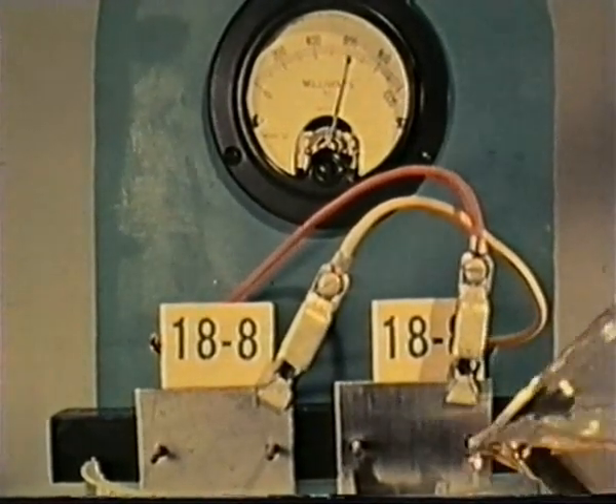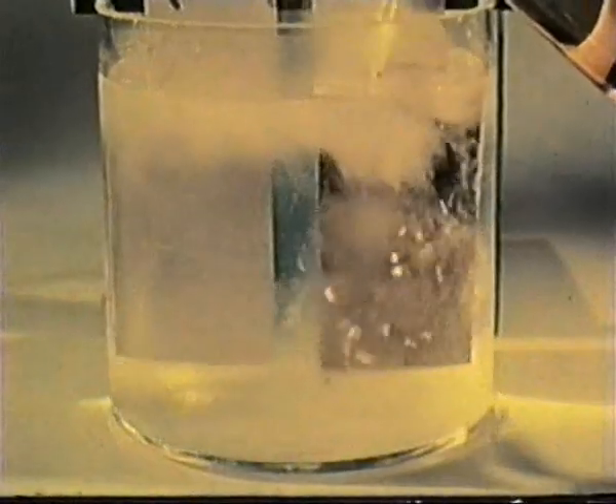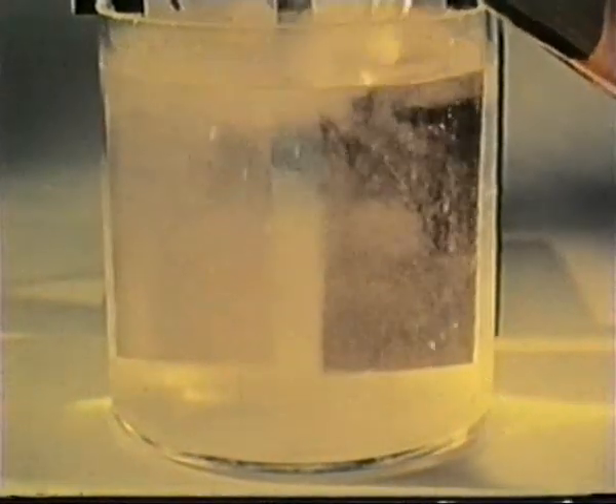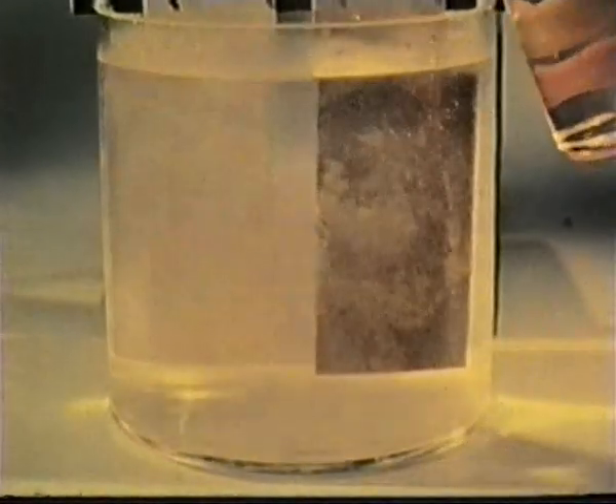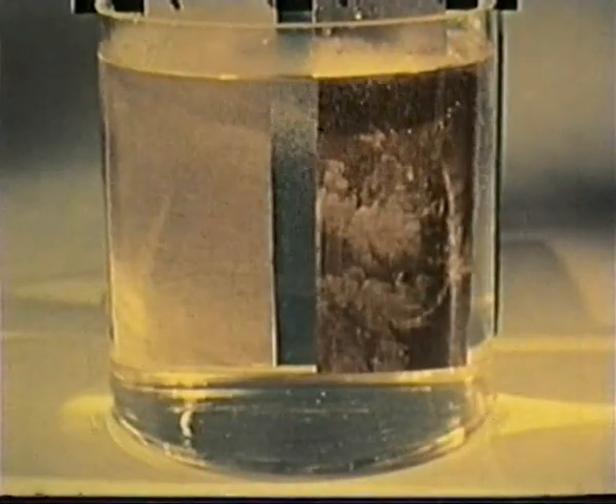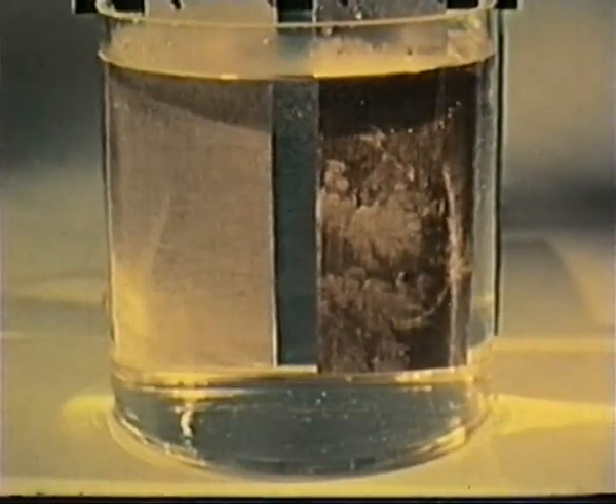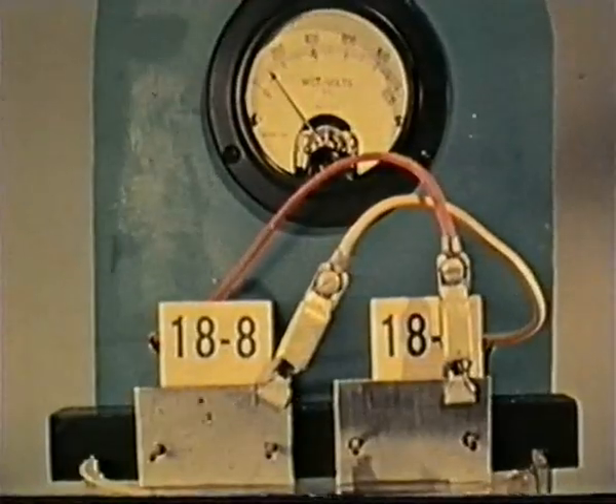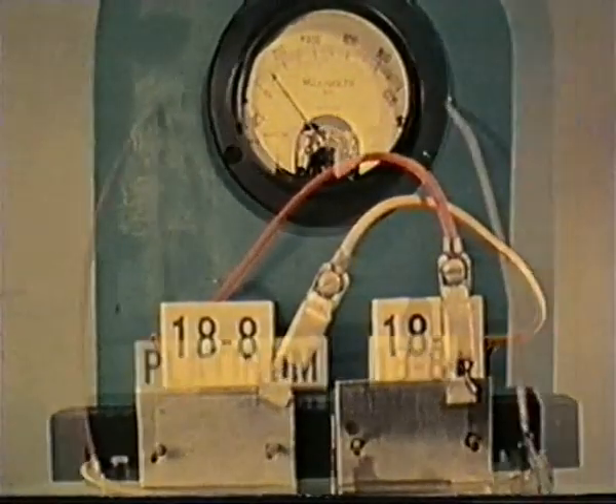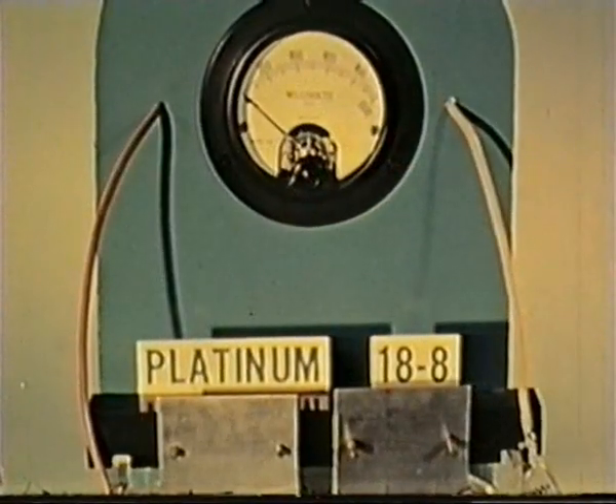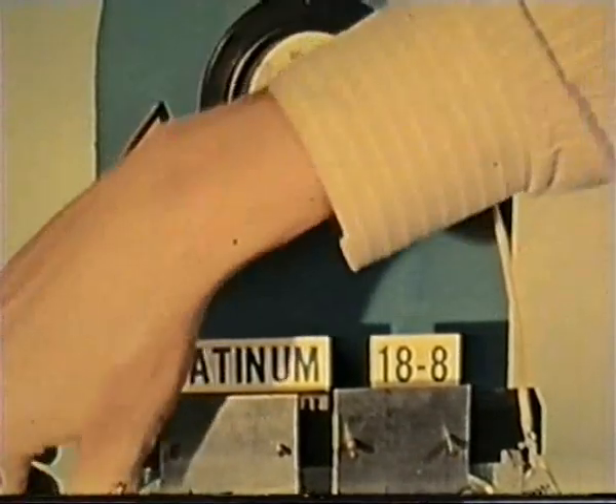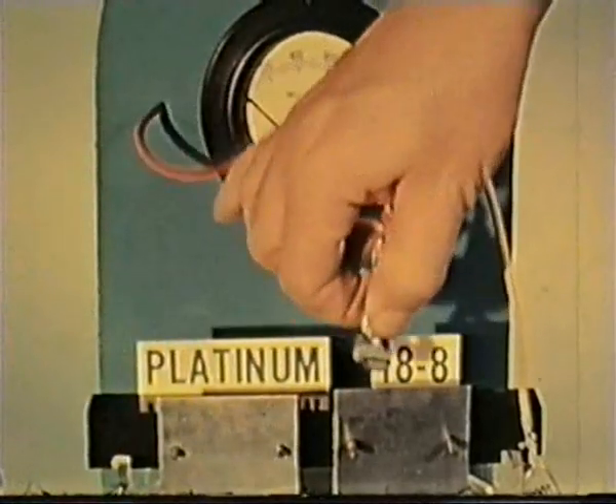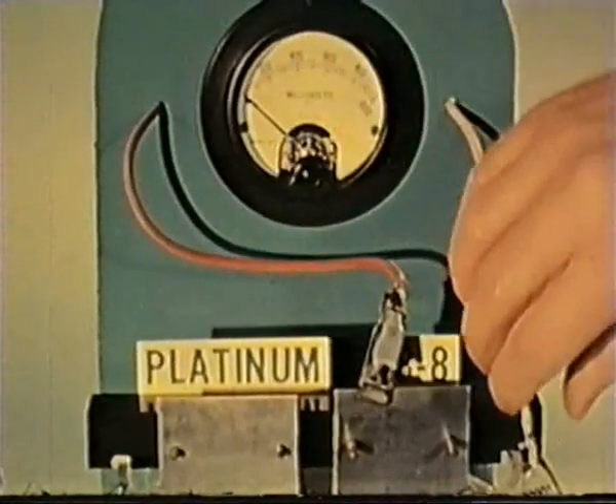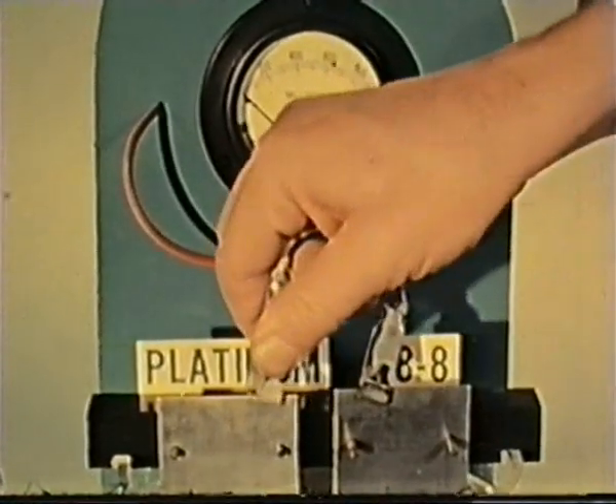We can restore the passivity of the activated stainless steel by introducing nitric acid, which has a strong passivating effect. We see that the evolution of hydrogen on the activated stainless steel stops, and the potential drops towards zero. If we then substitute a piece of platinum for the stainless steel that was always passive, we now observe a small difference in potential. This shows that the once active stainless steel has regained its passivity and its noble potential.